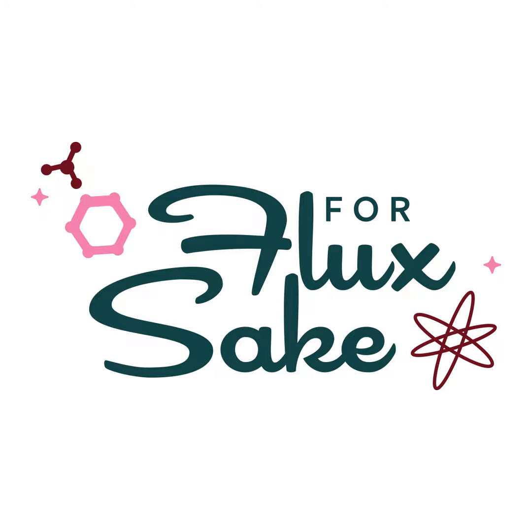And so the Bristol glaze is one of these eutectics. By combining zinc and calcium in the right proportion, they will go under cone 10. They're generally conceived of as being cone 6, but they can actually go as low as cone 2. I'm not saying to do that because it usually has to do with brick and long firings and all that kind of thing. But that's really what it is, that we're creating temperatures under cone 10 using materials that are more common, because lots of places will have zinc and calcium available as materials when they wouldn't have had boron or didn't want to use lead.